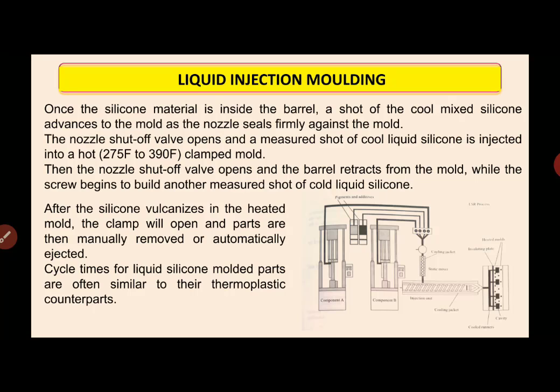Once the silicone material is inside the barrel, the shot of the cool mixed silicone rubber advances to the mold as the nozzle seals firmly against the mold. And the nozzle shut-off valve opens, and a measured shot of liquid silicone rubber is injected into the hot mold, usually 275 degrees Fahrenheit to 390 degrees Fahrenheit. Then the nozzle shut-off valve closes, and the barrel retracts from the mold, while the screw builds another measure for the next cycle, and the cold silicone rubber is accumulated.